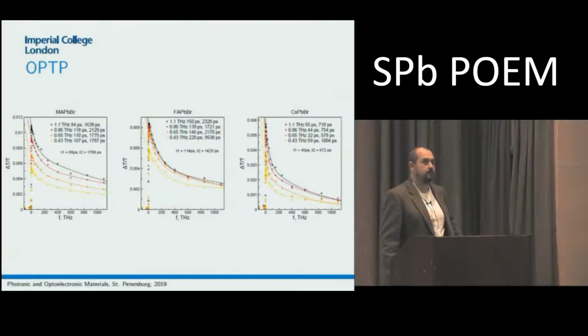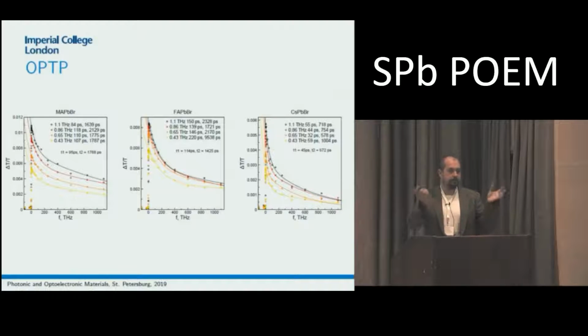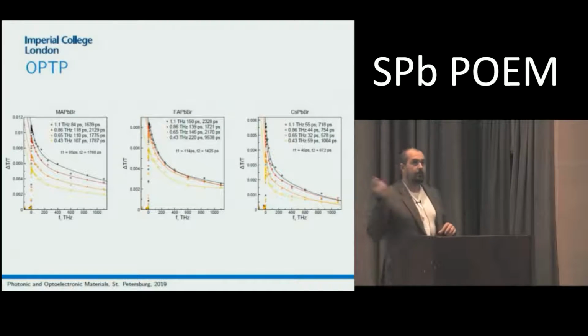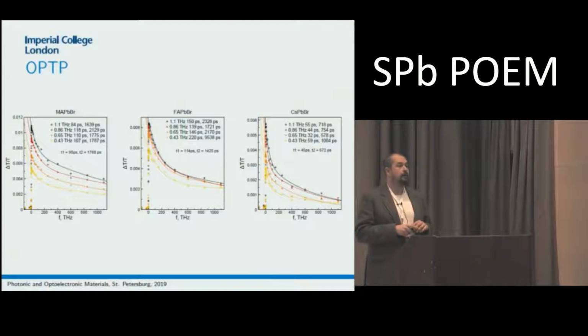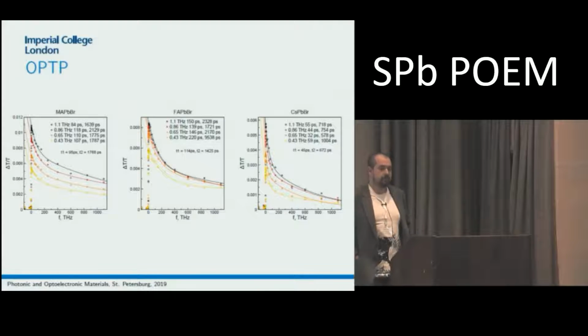Yeah, this is what is expected, and that's why we noticed that in cesium we have stronger interaction with phonons, and this is why the change of these characteristic times between the phonon lines and the other frequencies is so different in cesium lead bromide. Probably they should strongly depend on the temperature. I mean, if you heat your sample, this dynamics should really be looked into, and we're working on this. We have a cryostat, so we are going to see the temperature dependence as well.